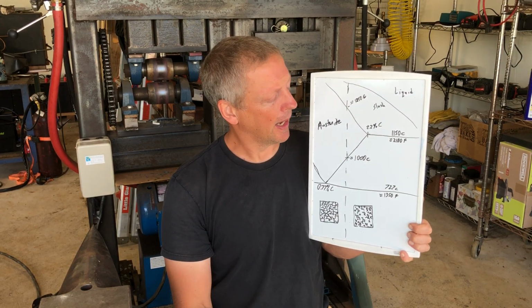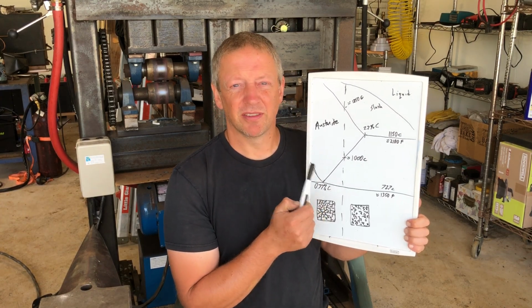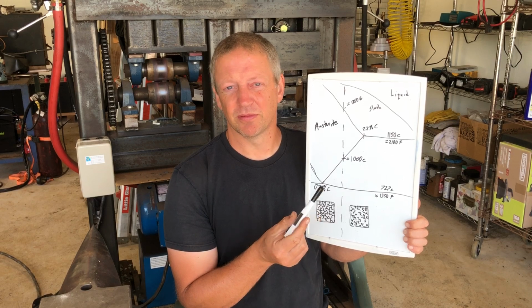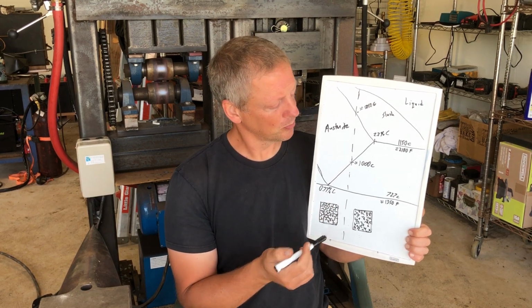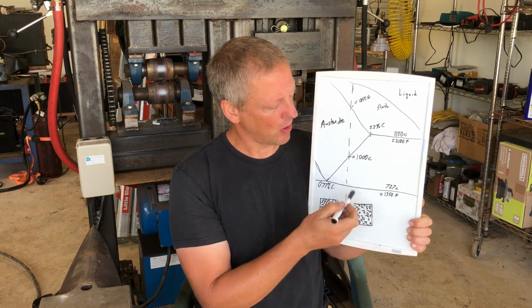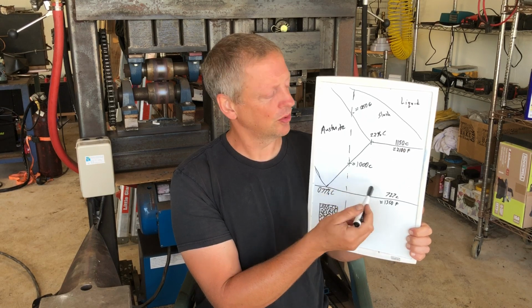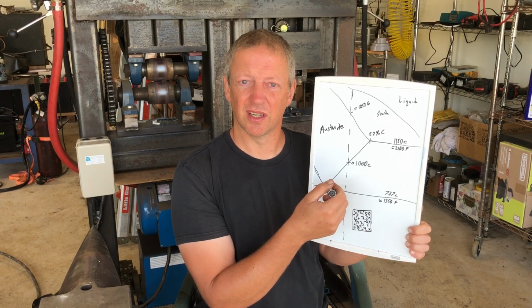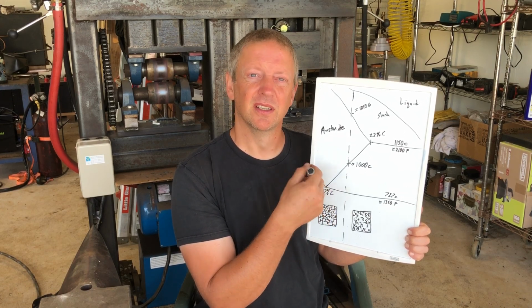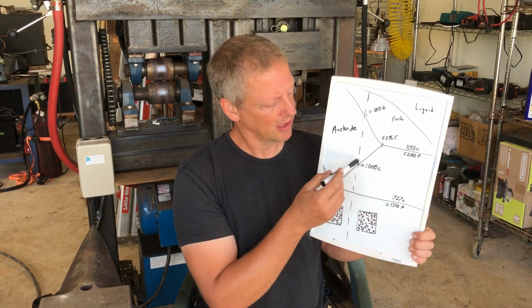So, things to keep in mind from this as you're deciding how you want to forge. Time at temperature makes a difference. If you've crossed into the austenite cementite area, how long you stay there really changes how much of the carbide dissolves, how much carbon goes into solution.